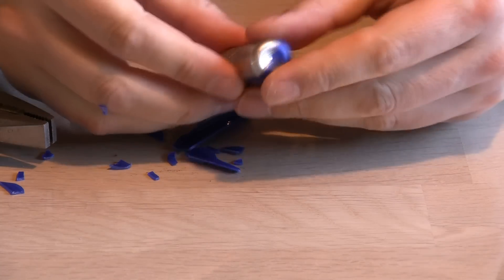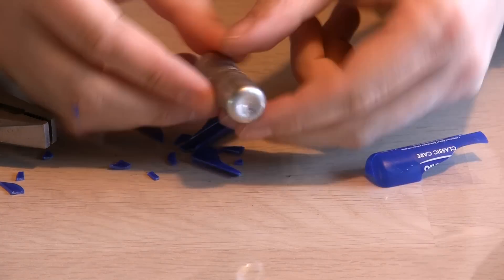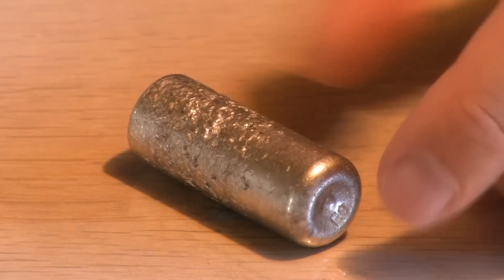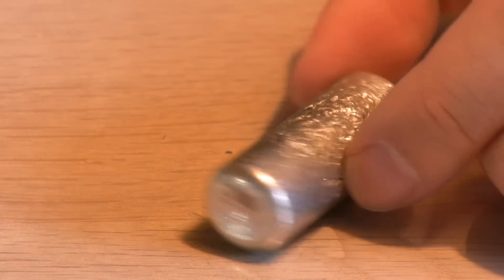After a little aggression therapy I brought out the right tool for the job. I'm obviously not a master caster. There are holes in my casting. I should have tapped the mold to get all air bubbles out. Ah well.